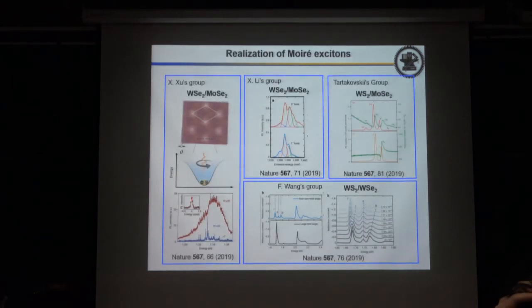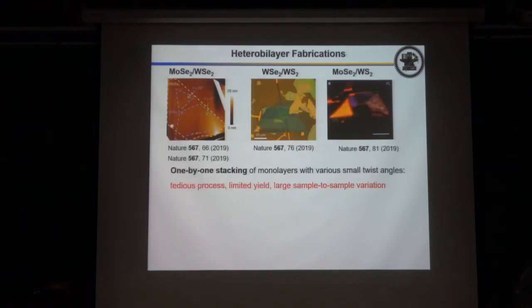So last year, actually in Nature, they already published about the so-called Moiré exciton in this kind of heterostructure. But they failed to reveal how the Moiré periodicity affects the excitonic state. Because if you want to study this, you have to fabricate many devices with different twist angles. So to be honest, this is very tedious, and the yield is very low. And you have to hire many graduate students to do the same thing. And then sample to sample variation will make you feel very frustrated. And now you give up.